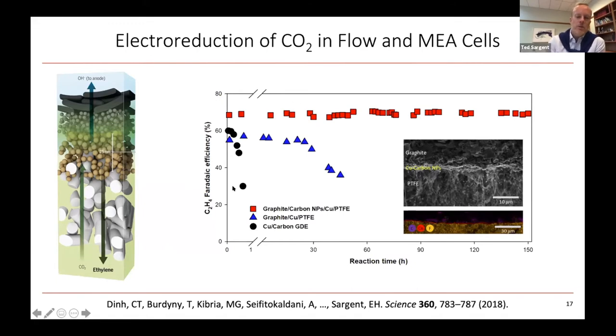And in this work from a couple of years ago, we were actually trying to figure out how to make a robust and reasonably long-lived system, you'll see an operating time of about 150 hours here, to study these CO2 reduction strategies in a flow cell environment. And what you'll see is that when we were just operating with copper on carbon, we found that within an hour or so, we could have water start to flood into the system. And we lost this gas solid liquid interface.